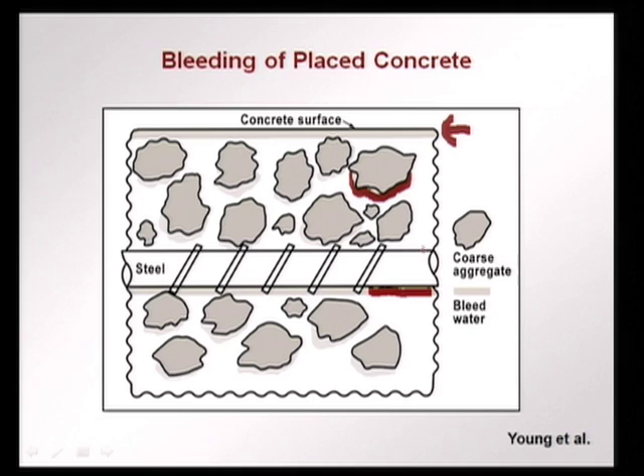Obviously, this cuts the bond between the reinforcement bar and the hydrated cement paste, and in the case of the aggregate we have a weak interface zone. So, this is something which really we do not want to have through the concrete. Use of properly designed concrete, use of mineral admixtures decreases the bleeding.